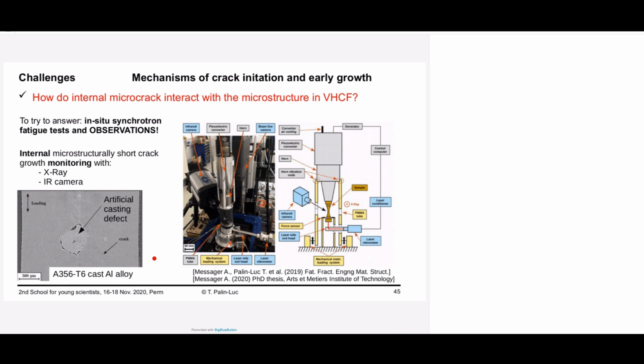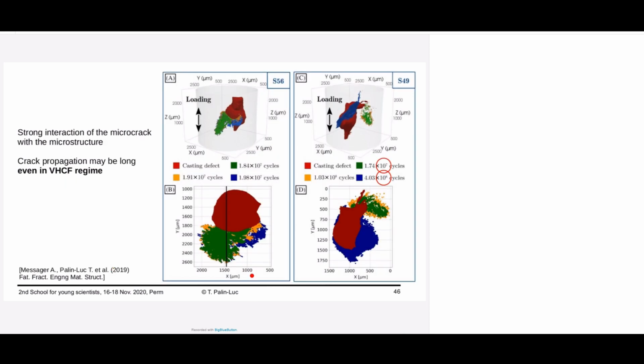And what we did is, with a specimen with an artificial internal defect produced by casting. So this defect is voluntarily put here in the center of the specimen in order to localize the area where we have to observe the phenomena. You can see here a crack. It is difficult to observe here because of the lack of light, but you will see on the next slide. So we were able to observe in situ, in direct, step by step, the evolution of the crack with a non-destructive technique.